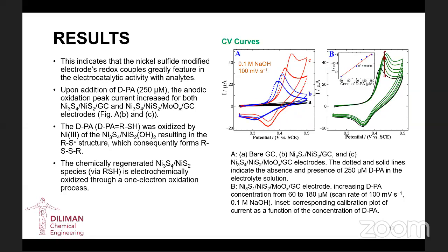And in this case, the DPA, which is represented here as DPA with the double bond connected to RSH, just to show the presence of the thiol group, was oxidized by nickel 3+ of the nickel sulfide phases, resulting in the formation of an RS• structure, which consequently forms an RSSR compound. And then the nickel sulfide phases or species are regenerated by an electrochemical reaction through a one electron oxidation process.